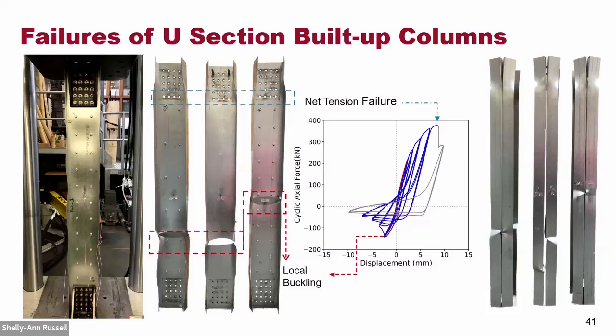And one specimen was just connected at the hold downs, but no fasteners were used. So you can see they behaved in different locations. You can see that the damage happened at different locations. And the fasteners keep the integrity of the specimens together, but it seems that they don't significantly increase the loading capacity of these sections.